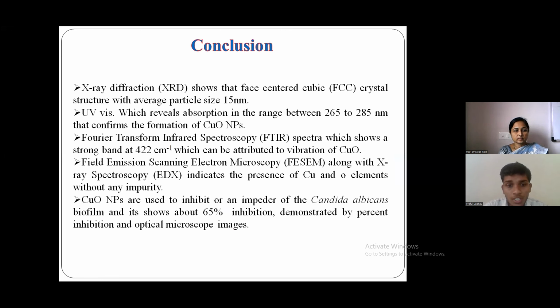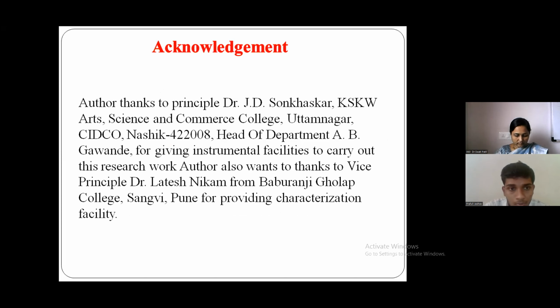Then FESEM along with EDX indicates the presence of two elements, that is copper and oxygen, without impurity. And then the copper oxide nanoparticles were used to inhibit the Candida albicans biofilm, and it shows about 65% inhibition, demonstrated by percent inhibition and optical microscope images.